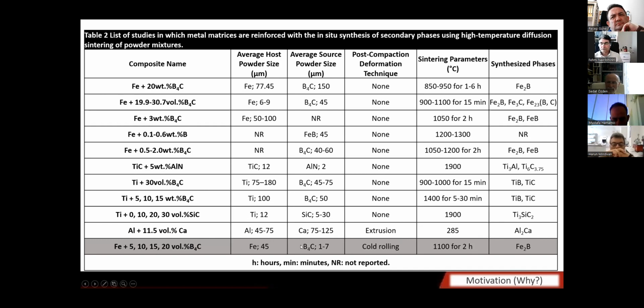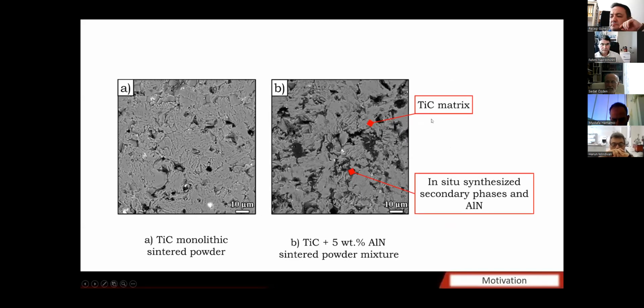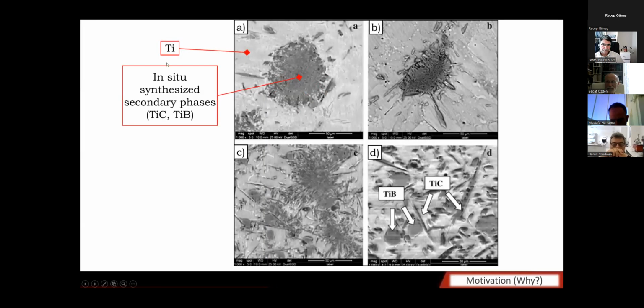This is my study, in which I have used cold rolling after the compaction, and I have also used elevated temperature sintering. My in situ synthesized phase is iron boride. Here is an example of the microstructure in which titanium carbide is reinforced by in situ synthesized secondary phases. Powder form without any phase, and powder after the heat treatment is strengthened by the secondary phases. Here is another example in which titanium is in situ reinforced by these secondary phases. So, metal reinforced by ceramic phases, chemical approach.